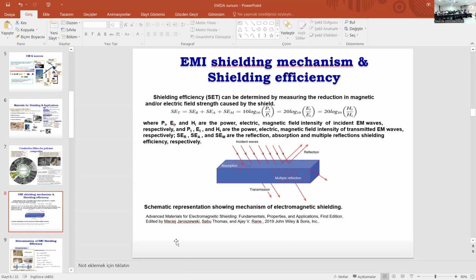Electromagnetic shielding mechanisms here represent the ability of the material to attenuate the incident EM radiation. There are three mechanisms that contribute to EMI shielding, namely reflection, absorption, and multiple reflection. The total EMI shielding efficiency is the sum of these three mechanisms. The reflection is related to the interaction between the conductive parts of the material and the impinging electromagnetic field, while the absorption is related to the absorption of the EMI waves by materials with high dielectric constant and high magnetic permeability.